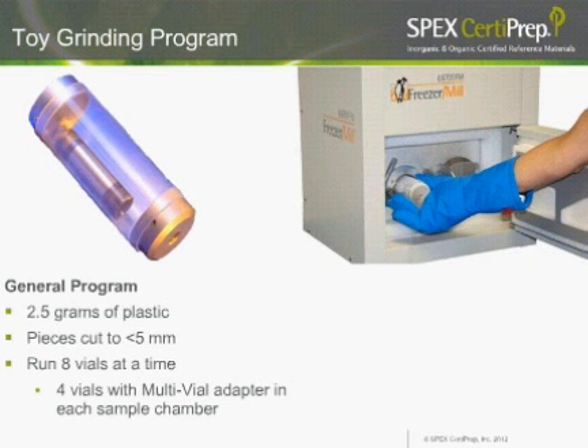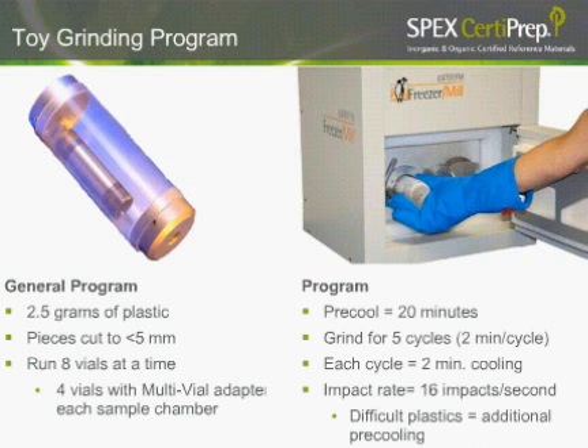For our program, we used 2.5 grams of plastic, and we cut these plastic toys down to less than 5 millimeter samples. We ran 8 vials at a time using our multi-vial adapter, so we had high throughput. We pre-cooled for 20 minutes. We wanted to make sure those samples were nice and brittle. And then we had 5 cycles of grinding at 2 minutes a cycle. Each cycle had 2 minutes of cooling in between, so there was no heating of the plastic. It allowed us to have a very nice fine powder at the end.